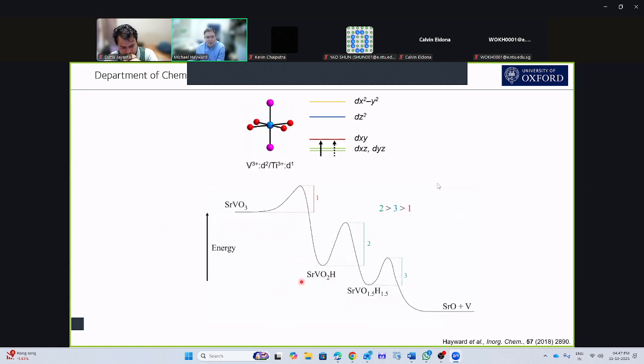However, if I take the system now where I've substituted some of the titanium for vanadium, sorry, other way around, some of the vanadium for titanium, I've taken out a few of these electrons. What that does is destabilize this t2g system. So I destabilize the O2H phase.